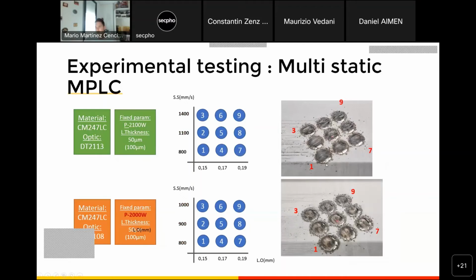But all in all, what we concluded from these experiments is that the secondary beam is delivering so much energy that the powder is being partially melted layer by layer, creating these balls, because the powder itself is not conductive. So it absorbs all the energy, and then it becomes this balling shape that you can see, which is very remarkable, especially in the contours, because in this place the powder is not being melted, right? But heated by the secondary beam.